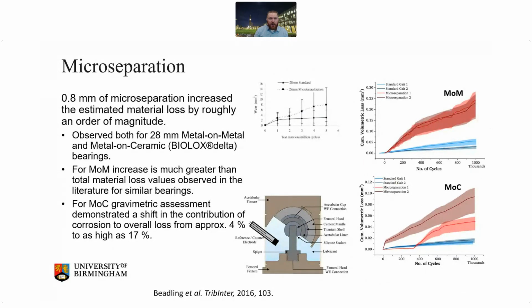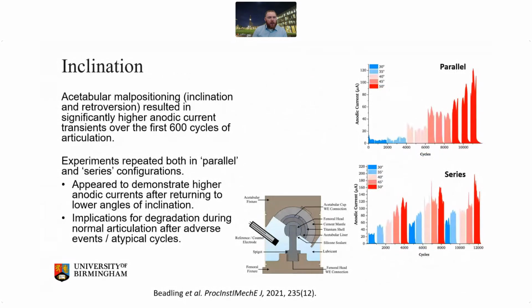So there was a shift from around, for metal and ceramic, around 4% to as high as 17%. So there's a change in the degradation mechanisms occurring there, that's not just a bulk wear rate, but important to how material is degrading and leaving the bearing surface, and then ultimately resulting in ions being released into the joint. Also looked at the acetabular inclination.